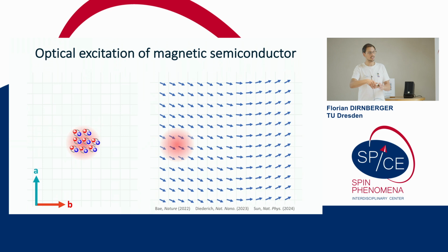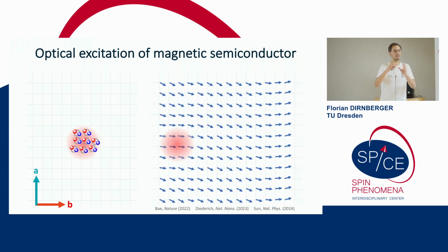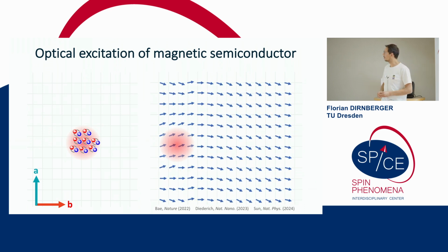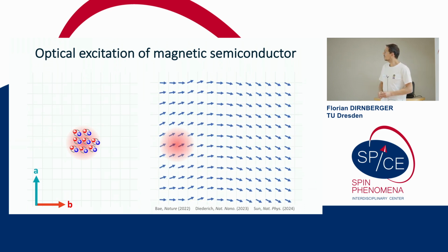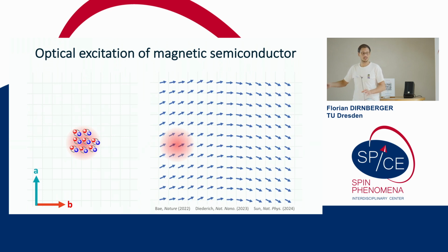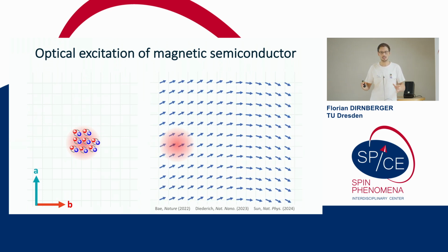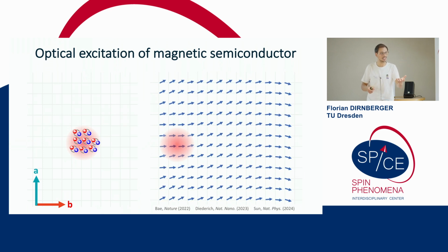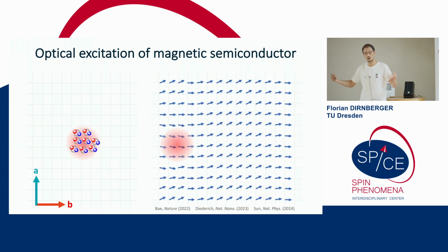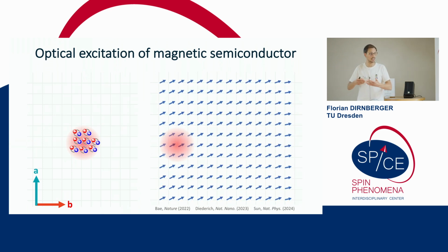So you shoot light, you locally maybe heat your sample, there's different processes that could be involved, but definitely you create a density gradient of the magnons that leads to a propagation of the magnons in this material. So in order to understand what the excitons actually do and how they move in the crystal, we believe that we have to account for both phenomena. The light pulse creates excitons, but it also creates magnons, and they're propagating. How does one affect the other?